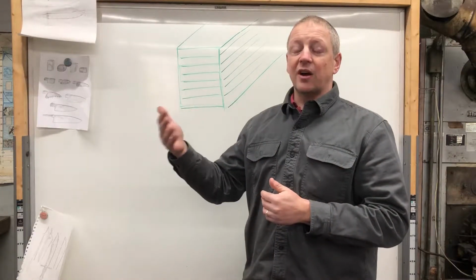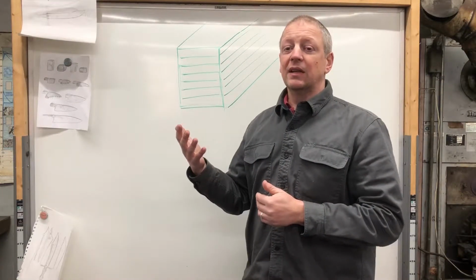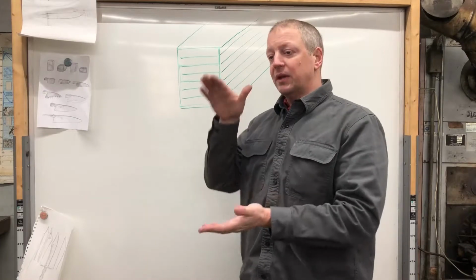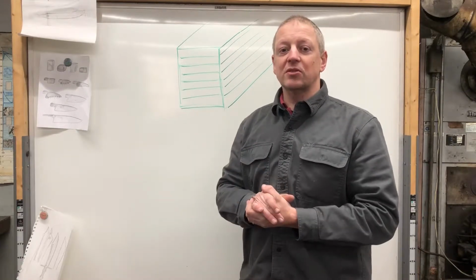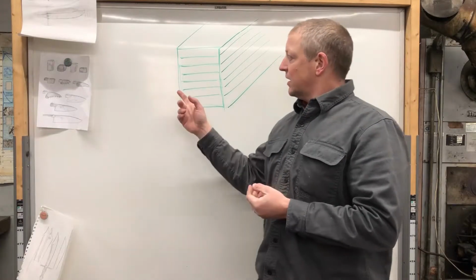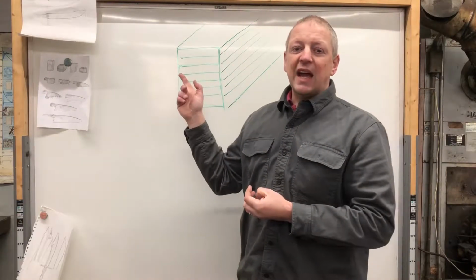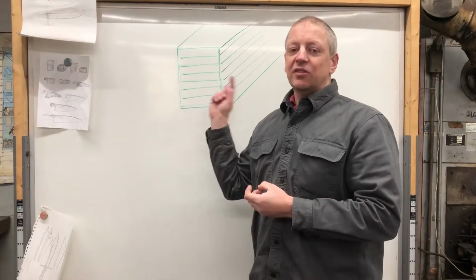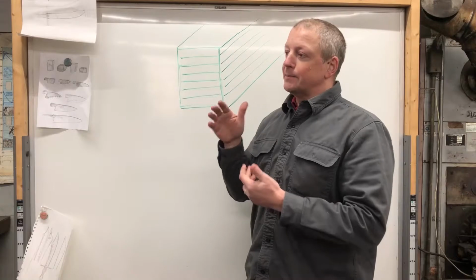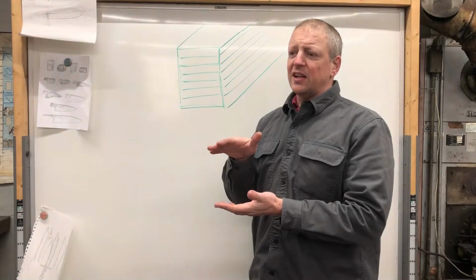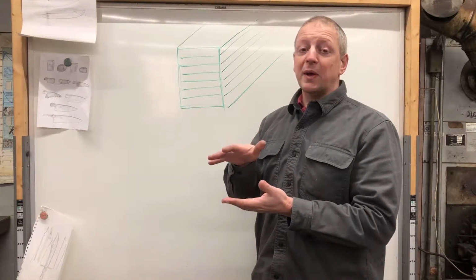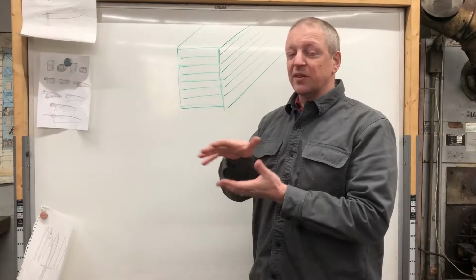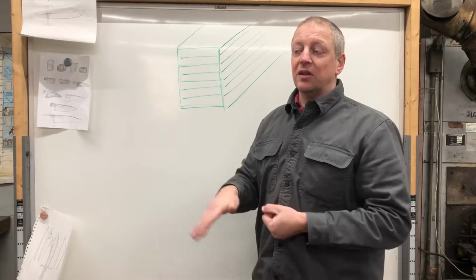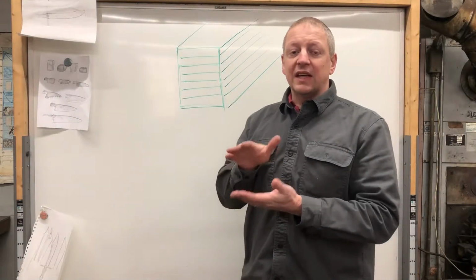Once your billet is starting to get pretty hot, it's not a bad idea to pull it out and just squeeze those layers together tighter. In your initial stack, almost certainly you've got some airspace. Very likely you're going to develop more airspace during the heating process. Things will have expanded and buckled a little bit. So squeeze that all together tight.